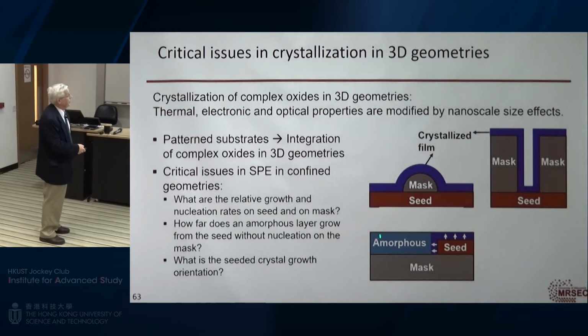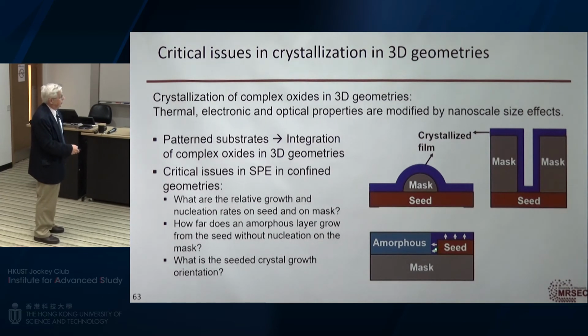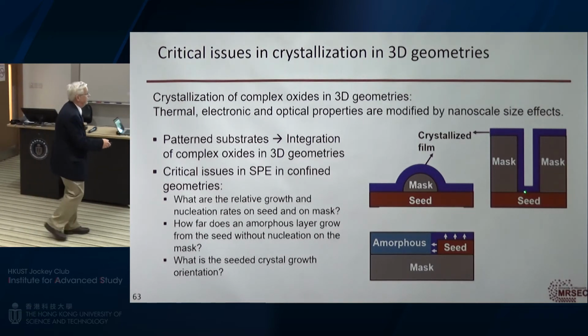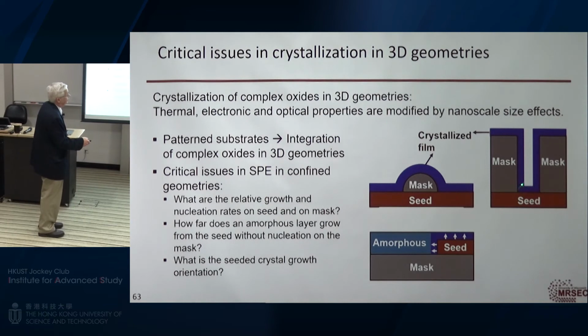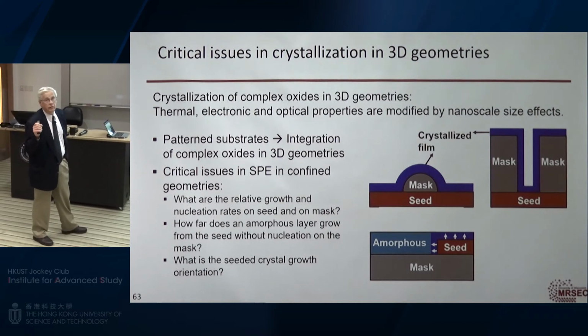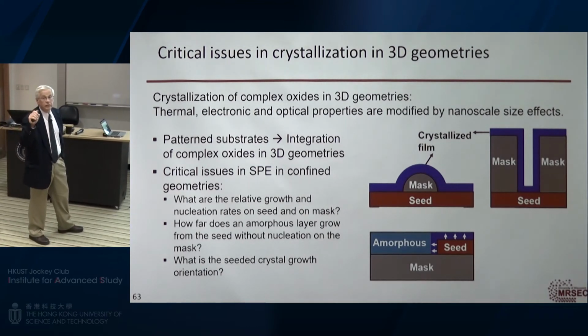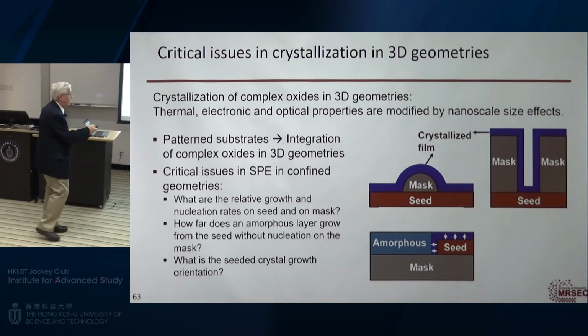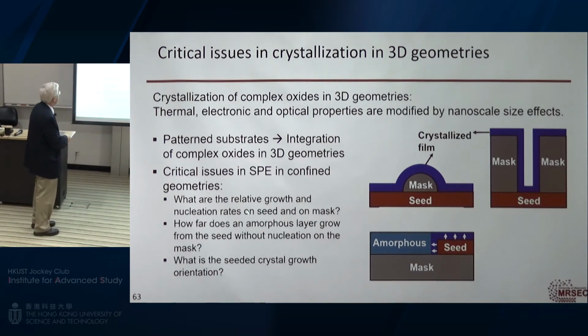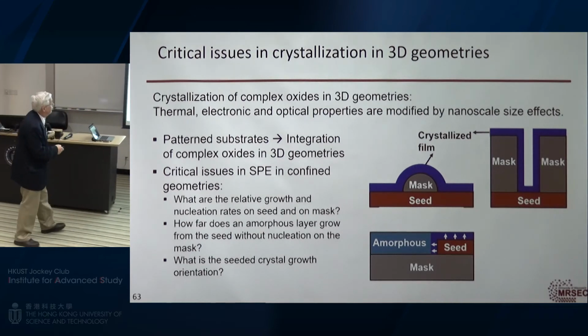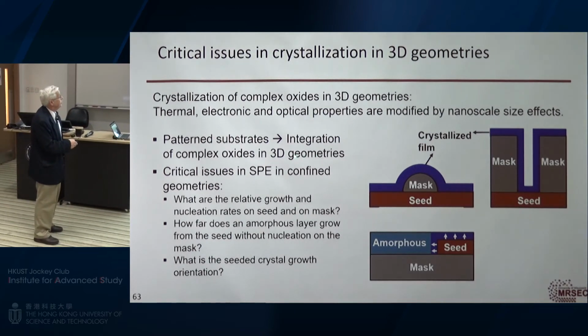And that amorphous layer could be in very odd geometries. So conceptually it grows out from the seed into the amorphous material. It could actually grow up and over in a single crystal or up around corners, because the crystallization front, where this was amorphous, is going to move up and through. And so we can use this to actually make single crystal nanostructures inside materials that I formed using the amorphous material to begin with. And so we're using patterned substrates to integrate complex oxides in three-dimensional geometries.